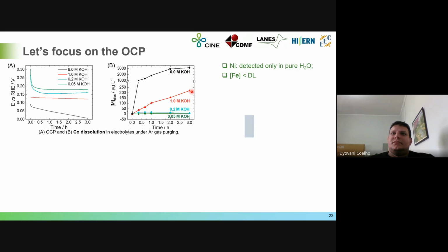But in 1 molar KOH, the same behavior. The catalyst is dissolved linearly over time. So it's just keeping the catalyst in solution, and someday the catalyst is completely dissolved. If we use a more diluted solution, we can see a lower cobalt dissolution. For iron and nickel, we just see the nickel dissolution in pure water, which means that the use of nickel in anion exchange membrane water electrolysis using purified water is not a good idea either, because we can't prevent the nickel dissolution. So we need to put some kind of alkaline in the medium just to keep the nickel stable over time. But for iron, we can't see any iron in the electrolyte during the open circuit potential.